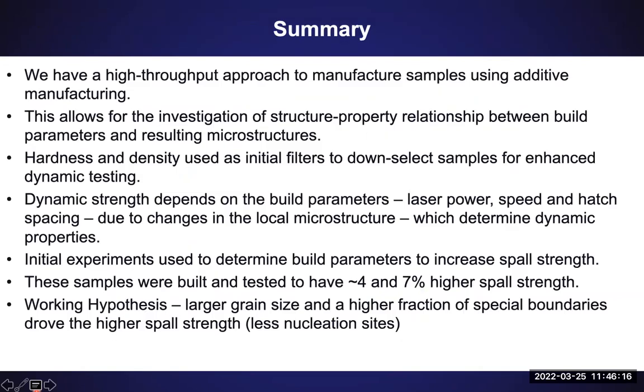So in summary, I would say that we have a high throughput approach that we're using to make samples. There was a lot of work that went into making this process high throughput. You know, we didn't want to make 5 samples a week. We wanted to make hundreds of samples a week and rapidly screen them using properties like hardness and density. When we performed dynamic testing on these samples, we were indeed able to increase the Spall strength of the materials by 4 to 7%. We are working right now on some other processing techniques to see if we can increase the Spall strength of these materials even further.